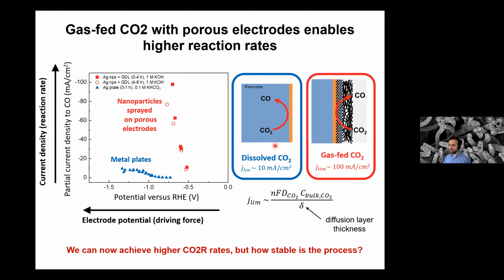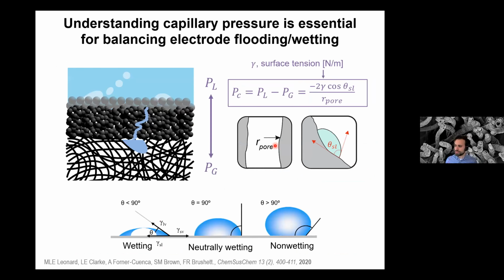And what we are basically doing in the field now is repurposing a lot of the knowledge that has been developed for fuel cells. So a lot of the GDE concepts that are used now based on carbon fibers and microporous layers were driven from fuel cells. But there are several unique challenges, I believe, for CO2 electrolyzers that motivate the development of radically new material concepts. And one of these problems relates to, again, multi-phase transport, and I'm recalling the same equation that I used before, the capillary pressure that determines the transport of liquids when there are liquids and gases. It depends on the contact angle and the pore radius. But all this material development was performed for water, right? Because fuel cells and electrolyzers basically ran with water.